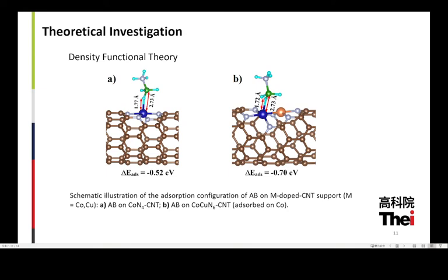For the theoretical investigation, we calculate the optimized structure and illustrate the simulation result in these two figures. Our preliminary study confirmed that modulating the environment of single atoms' active site to alter the electronic structure is a reliable strategy for boosting catalytic activity.